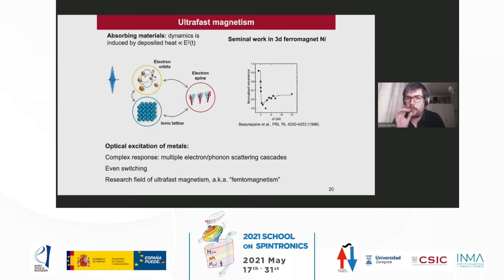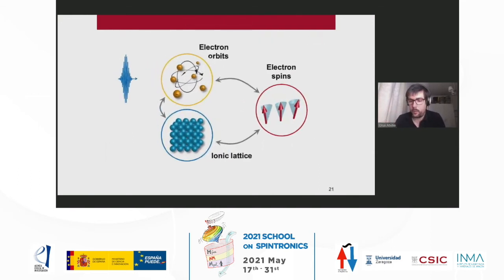What they observe here is that the magnetization reduces to half of its value in the order of 1 picosecond, and then the magnetization recovers. This was in nickel 25 years ago. Since then, many people, including me, have been investigating nickel and other 3D materials and many other magnetic materials.